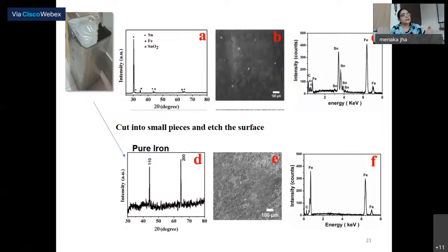I tried to etch the surface, because normally when we cut it and do the cross-sectional assessment, you will find around a 2 micron thick layer of tin coated onto the iron, the steel surface. So I tried to etch this thin layer and get pure iron. I looked at the surface of that pure iron and got a very rough surface, and then I looked at its EDAX again. All the tin was removed. So I developed this protocol, a simple acid etching protocol.